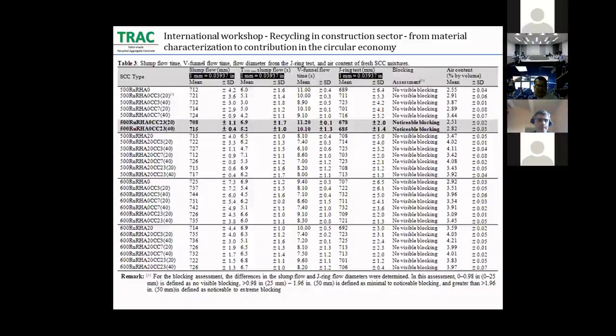Furthermore, calcium carbonate also improves the slump flow of self-compacting concrete at 600 kilograms per cubic meter more than at 500. This improvement occurred due to the increase in powder content, which also increased the amount of paste in the self-compacting concrete. With the use of rice husk ash as fine aggregate replacement, the smallest calcium carbonate particle size can also disperse and fill the voids of rice husk ash particles, which improves the flow value.